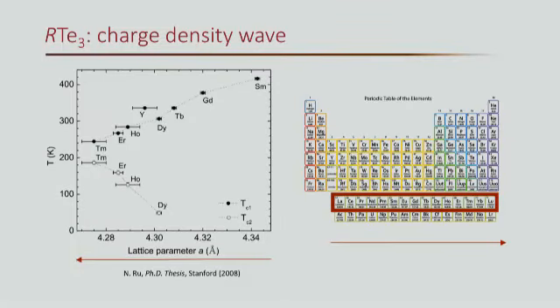So the entire series, you can see from the periodic table here, all of them exhibit charge density wave transitions. Here, actually, I'm only plotting part of the series, because for lighter atoms the transition temperature is rather high. In particular, for the specific case of lanthanum tritelluride we study, which is really the first atom in this series, the transition temperature is so high that it's probably above 600 Kelvin, pretty much close to the destruction limit of this sample itself.